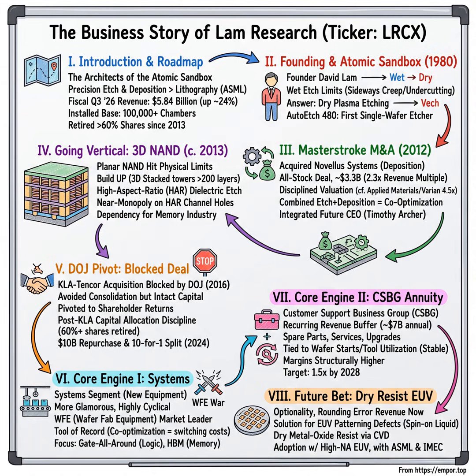Lam has concentrated on the steps where its physics gives it an edge, particularly the exquisitely selective etch that removes sacrificial silicon-germanium layers without so much as scratching the adjacent silicon channels, and the deposition of the inner spacer that insulates the structure. The honest framing, though, is that this is contested ground. Applied Materials is pushing hard to integrate these very steps into its own platforms, and the GAA transition is precisely where Lam's logic moat is most exposed to attack, a thread we pick up in the bear case.